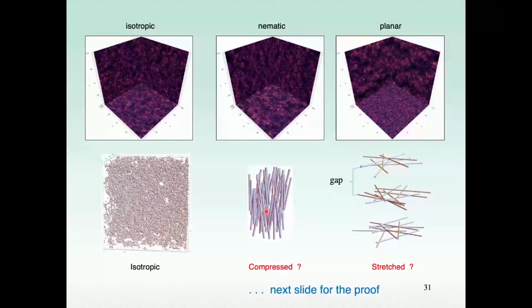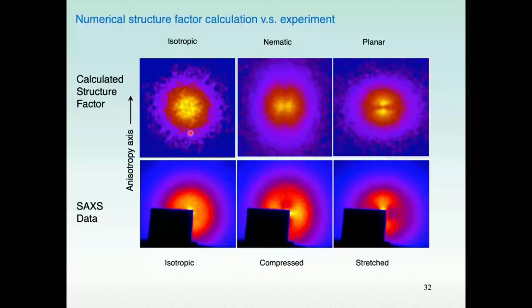And the result here, the proof of this comparison, comes from an analysis of the numerical aerogel, where the team has calculated the structure factor, which is the Fourier transform of the pair correlation function. And you can compare that directly with the small angle X-ray scattering. And for an isotropic numerical aerogel, or from an isotropic experimental aerogel, you can see that we have nice circular symmetry in the diffraction of the X-rays and the behavior of the calculated structure factor. However, in the anisotropic aerogels, the identification of this horizontal intensity in the structure factor corresponds rather closely to the compressed aerogel, and that's the reason why this nematic case we're associating with compressed aerogel, interestingly.